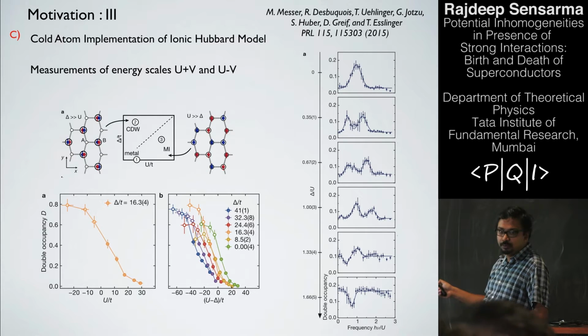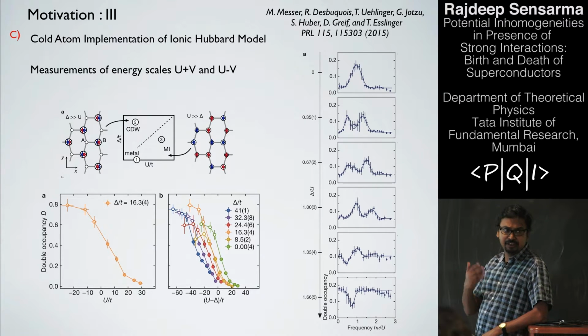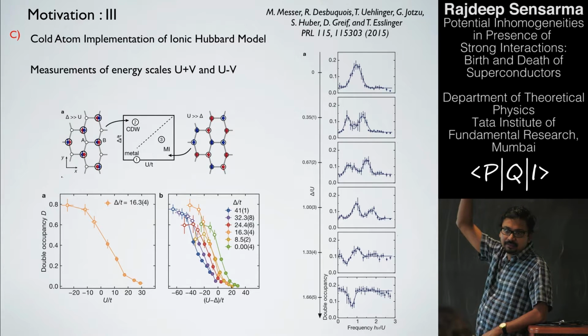So this is U. But once delta starts becoming finite, what you see is that you break it into two pieces: one is U plus delta and the other is U minus delta. That's because if the double occupancy is created on the A sublattice, it's U minus delta. If it's created on the B sublattice, it's U plus delta.